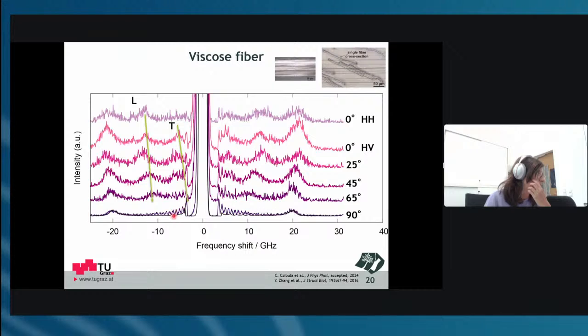So what you see here, these rough oscillation-like things, this is coming from the surface of the fiber, coupling into the spectrometer, and you will not see any peaks there, because it's just overlaying signal and noise, which is very, very dominant on all the fibers, I must say. As soon as you get to a vertical alignment of the fiber, it is very difficult to resolve peaks anymore. But we could determine at least the longitudinal peak and the transverse peak.